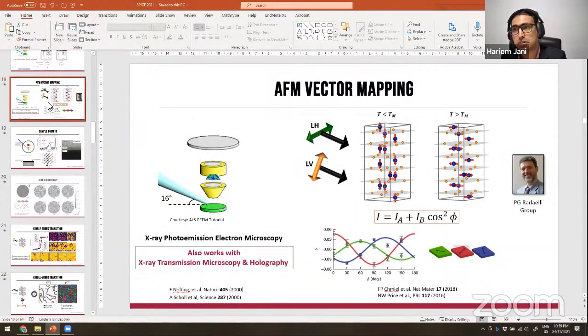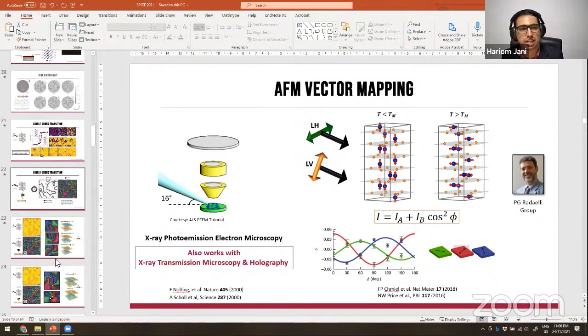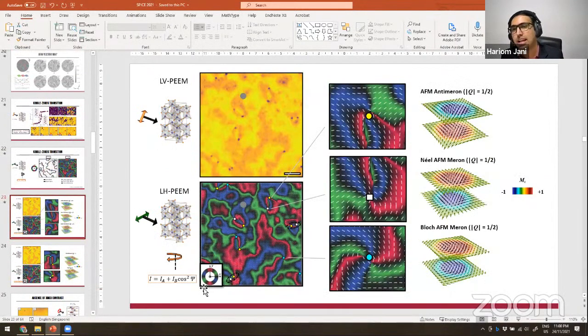What we actually do is perform linear horizontal imaging of the entire area in one shot, and then we rotate the sample one by one, and collect various phase values phi relative between the X-ray polarization and the sample angle, which allows us to construct the variation of the dichroism across the entire image. Due to the variation of the dichroism, it is then possible to fit this data pixel by pixel, the contrast, and that allows us to assign a unique value of the antiferromagnetic phase. That fitting process then allows us to attribute a value of RGB, which corresponds to the orientations shown on the color wheel here.